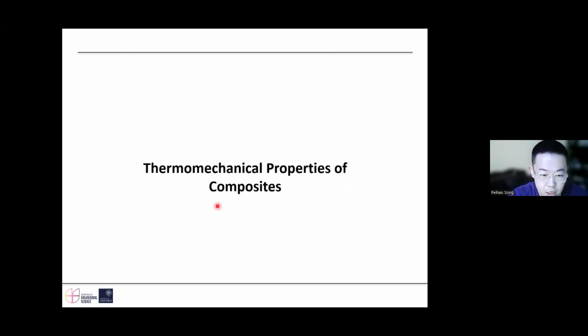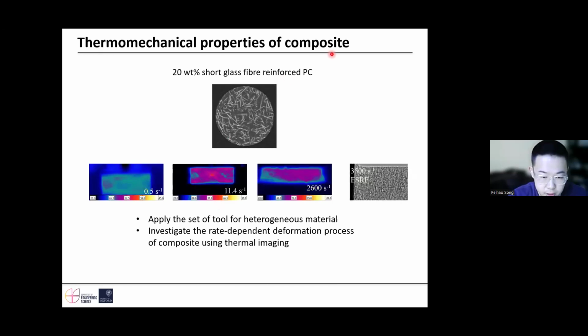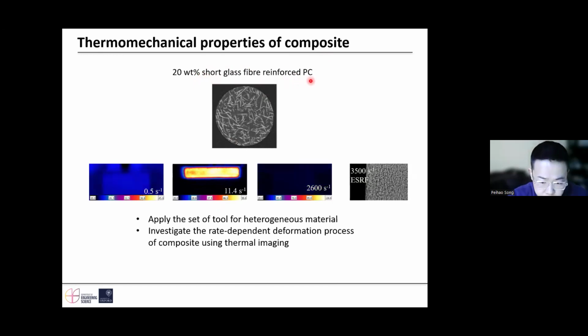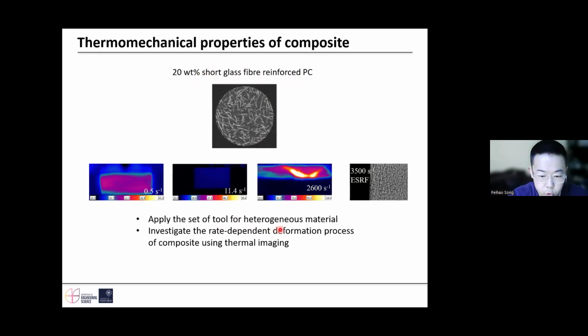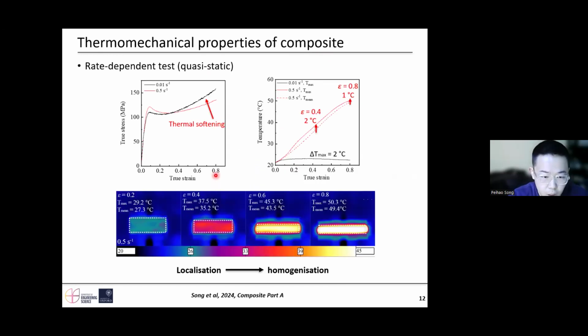After understanding what really happened during small and large strain for the polycarbonate, I characterized the thermomechanical properties of a polycarbonate composite. Here is a 20% short glass fiber reinforced polycarbonate. I applied a set of tools to this heterogeneous material and investigated the thermomechanical properties. So here is a rate-dependent test at quasi-static.